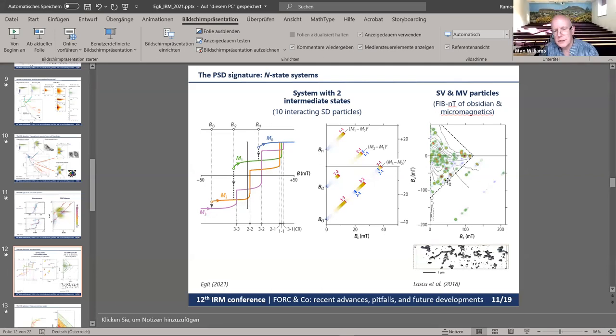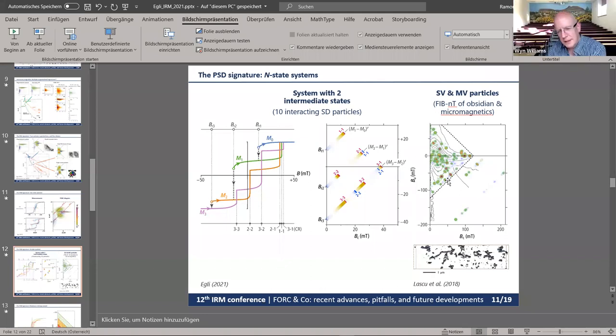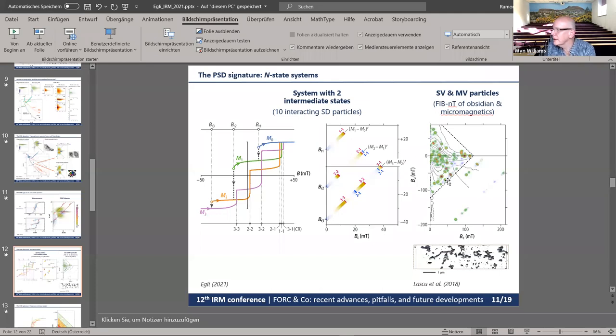Rich adds a comment and compliments the talk. He asks about the bacterial chains and double strands, referring to the Chang paper results. He notes that simulating single chains as a function of degree of collapse, the most collapsed chain gives a remanence ratio not so far from the experimental values shown. He wonders how universal the orange trend curve is, and whether playing with parameter space for single chains with different degrees of collapse and particle separations could reproduce the lobes seen. Ramon replies that the simulations modeled chains as they are from electron microscope examples without adding extra randomness, but doesn't exclude other structural changes.